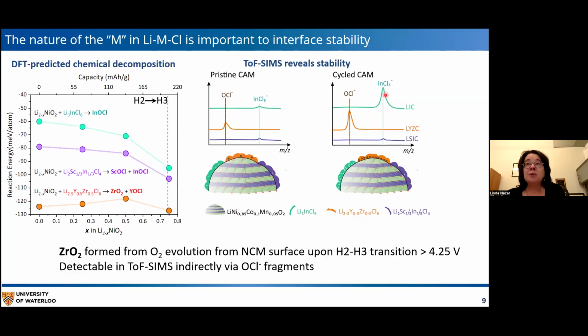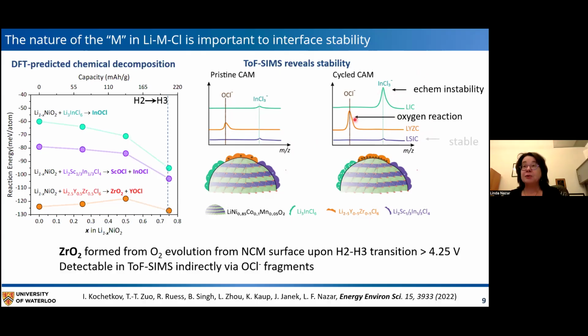In the case of the lithium indium chloride, we see a feature of the indium chloride fragments, which indicate some electrochemical instability at that potential. And again, that's not really surprising. But you can see in the case of LSIC, which really functions the best in terms of cycling stability, that there are no traces of either oxychloride or the metal chloride. So this is coincident with its electrochemical stability. And so this is just showing that this is the feature of the electrochemical instability. This is the feature of the oxygen reduction, whereas we have a stable LSIC material. So it's not just the question of the metal chloride itself being stable at the interface. The nature of the metal in the metal chloride is important to interface stability, is the conclusion.